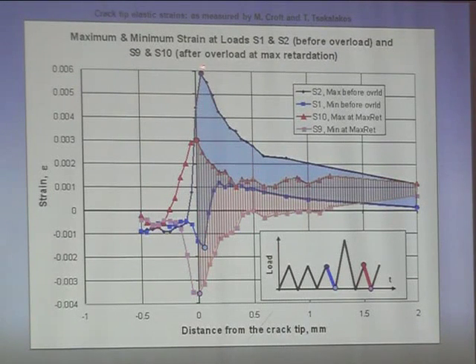So what we get here is that overload reduced the maximum elastic strain ahead of the crack tip in a significant way. This experiment showed that there was also a reduction of minimum elastic strain, but if you put the total strain together with stresses, you see very little change in stresses. So that was kind of qualitatively confirming what I was doing, because the hysteresis loops which I was showing were the elastoplastic strain. Here we see only the elastic strain.